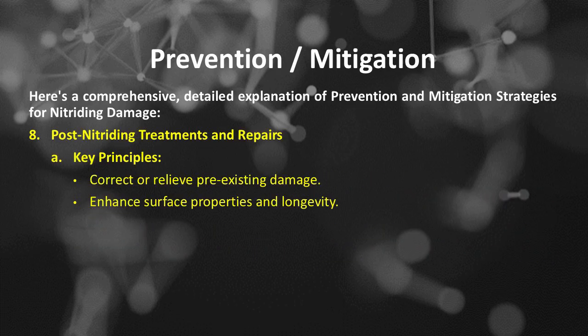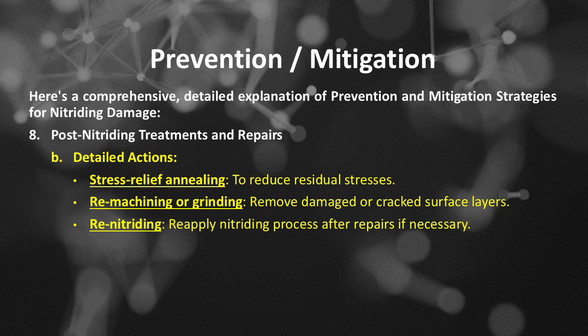Number 8 of prevention and mitigation strategies for nitriding damage is post-nitriding treatments and repairs. The key principles include: correct or relieve pre-existing damage, and enhance surface properties and longevity. Detailed actions in post-nitriding treatments and repairs include stress relief annealing to reduce residual stresses, remachining or grinding to remove damaged or cracked surface layers, and renitriding, reapplying the nitriding process after repairs if necessary.